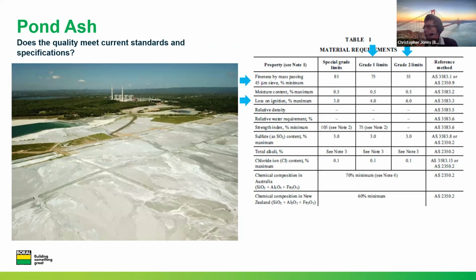So the question is whether pond ash will comply with the Australian standard. In the Australian standard AS 3582.1, there are 3 grades of fly ash. The special grade is used for high performance concrete in a similar way to silica fume, which is not relevant for today's discussion. So that leaves grade 1 and grade 2. The main difference between them is their fineness and their carbon content. The carbon content is measured by their loss on ignition.